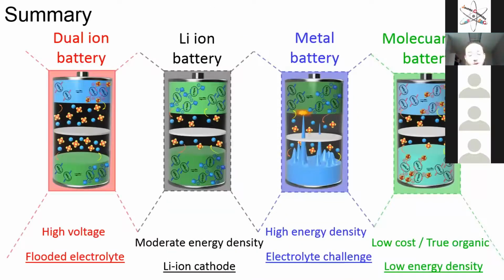So to summarize, I have shown you that we can implement organic materials in 4 possible battery configurations. The first one is the dual ion battery. The most important thing that you need to keep, if you want to work in this field, is the high voltage. But the challenge here is the electrolyte and the capacity. You need to find some p-type materials at the cathode that can store high capacity. And the other one, the lithium ion battery, is more promising, can provide a moderate to high energy density, but the challenge here is the lithium containing cathode. You just need to have a lithium containing, high voltage and air stable cathode.